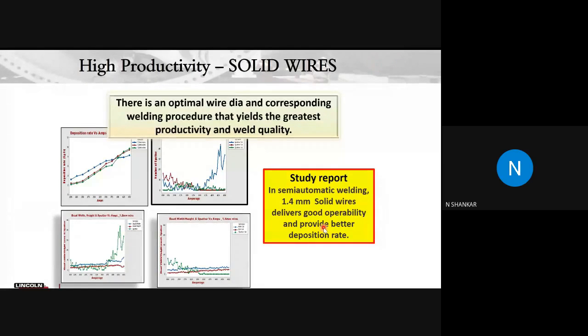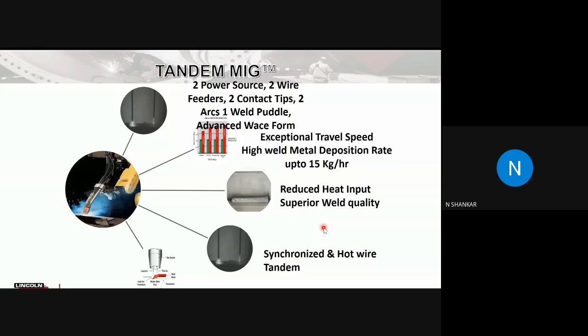I'm not saying the maximum deposition, I'm saying the optimum deposition. Means good quality weld, with the required mechanical properties, penetration and quality parameters, everything meeting, and you have a higher speed. So optimization comes at 1.4 mm for the manual process. That is what we studied. So this made us realize that increasing the wire size is not the only solution.